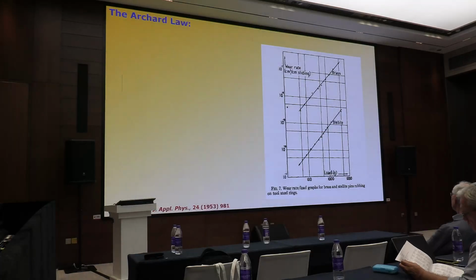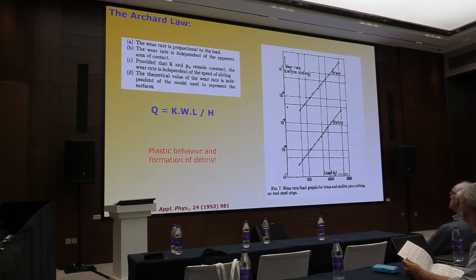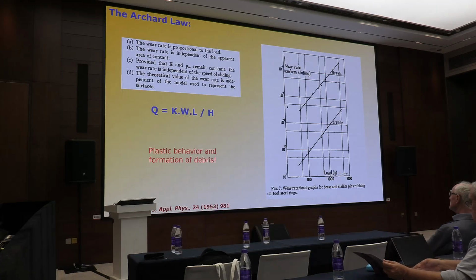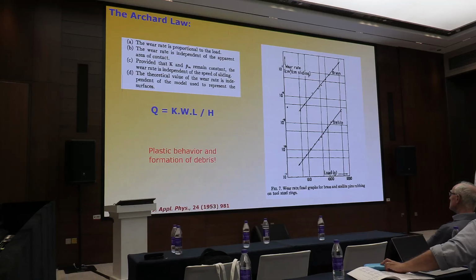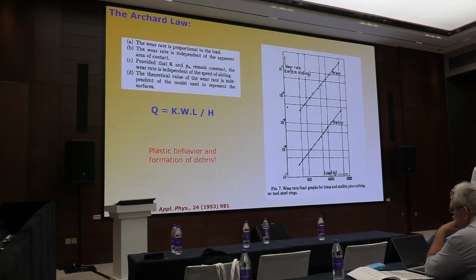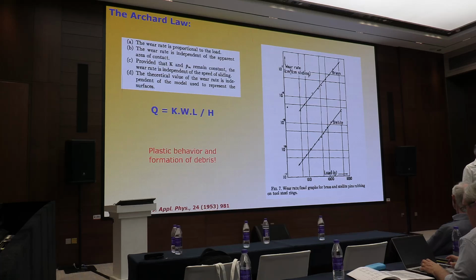This is for stellite and brass. You can see that this depends on the hardness. Another condition for the application of this equation, this Archard law, is the plastic behavior and deformation of the brass. You need deformation because you have wear, you have to remove the softer material, and you also need plastic behavior, because with elastic behavior it's difficult to remove material. You have to create this deformation due to plastic behavior and then remove the material.